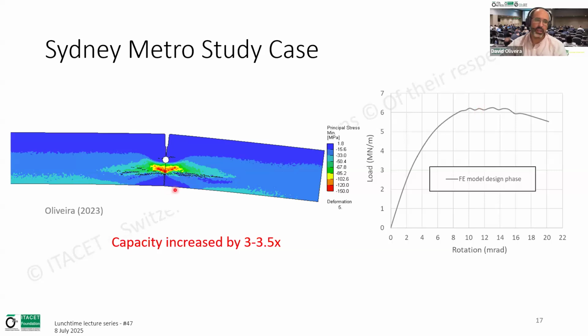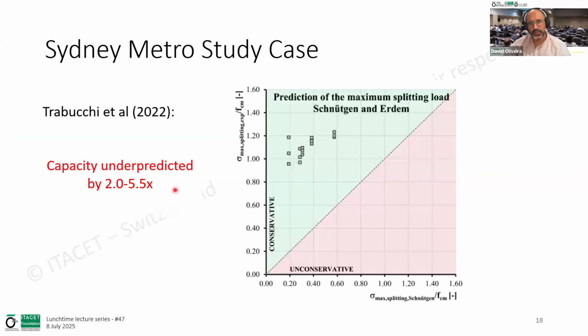So of course, when we start getting this sort of 'wow, this is too good to be true', we started investigating a bit further. And at the same time, we were lucky to find the work by Trabucchi, almost happening parallel to what we were doing. That was demonstrating that the model by Schnütgen and Erdem was generally severely under-predicting their experimental work. So you can see here, it was under-predicting by 2 to 5 times.